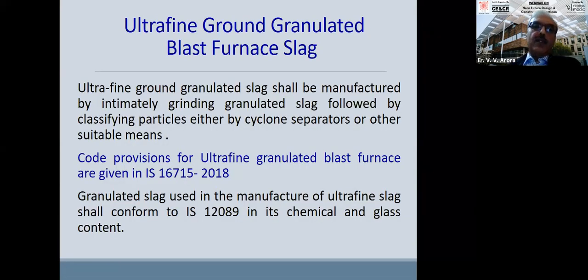Now, this is a newer thing, ultrafine ground granulated slag. One is the granulated slag which we just discussed, where we use 50 to 70%. But the same slag, when ultrafine grinding is done, becomes a kind of replacement for silica fume, which gives you more pore filling effect as well as the pozzolanic effect. Cementitious properties are also there. Code provisions for ultrafine granulated blast furnace slag are given in IS 16715-2018.